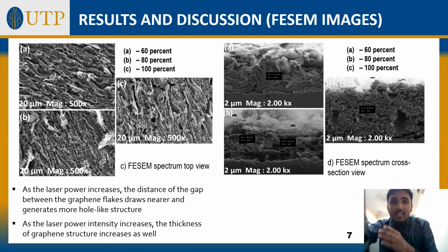On my right side is the cross-section image of the laser scribed graphene with 2 micrometer and 2.00 kX magnification. In these images, you can see a specific reference point. It shows that the thickness increases from 21.61 micrometer to 25.69 micrometer to 36.07 micrometer as the laser intensity increases from 60% to 100%. So for my last results in discussion, I would like to talk about the electrochemical impedance spectrum. There are three main graphs I'd like to talk about.